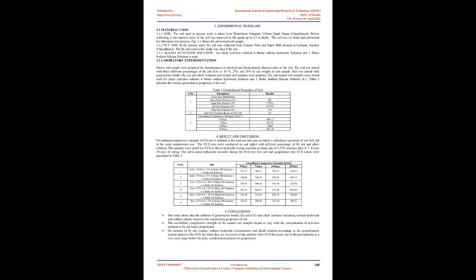The molar concentrations of alkali solution, M, used were 4 molar, 8 molar, 10 molar, 12 molar, and 14.5 molar. Ratios of alkali solution to binder were varied from 0.45 to 0.85 for geopolymer synthesis. Samples were compacted at a consistency of plastic limit with a tamping rod to remove air voids.